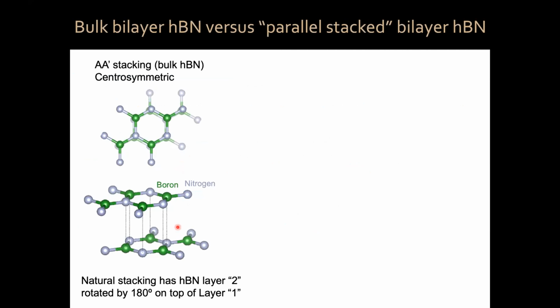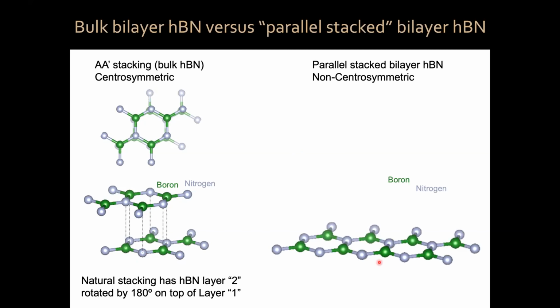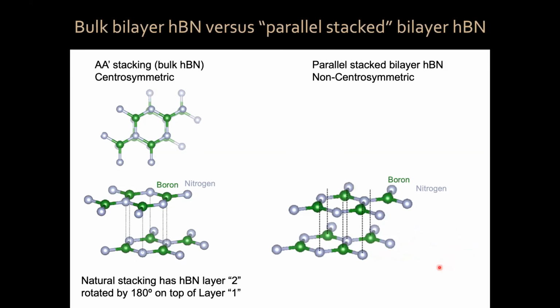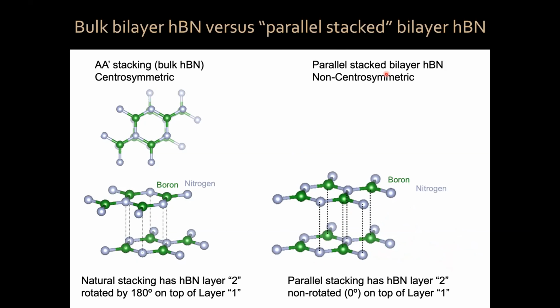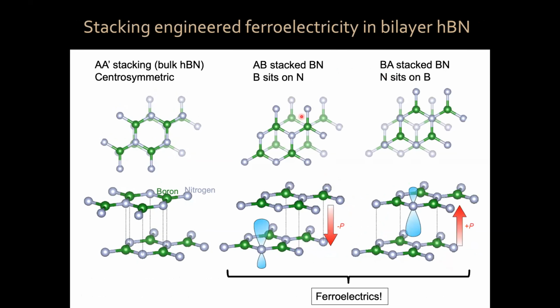And this is because, again, we can do something very interesting with these 2D materials. If you take hexagonal boron nitride, the substrate that we put our graphene devices on, it's also a honeycomb lattice, and the natural stacking is AA prime, boron atoms on top of nitrogen atoms. But if you take a monolayer of boron nitride, break it in 2 pieces and stack it on top, now all of the atoms are on top of themselves. The parallel-stack bilayer hBN is non-centrosymmetric, which is very uncomfortable for the system, so the system decides to go into these AB and BA stacking configurations, which have a finite electric dipole moment that can be switched with an electric field. So this turns into a ferroelectric.